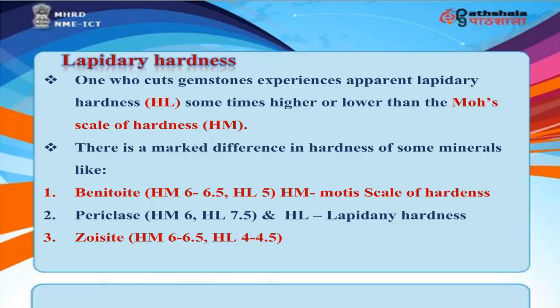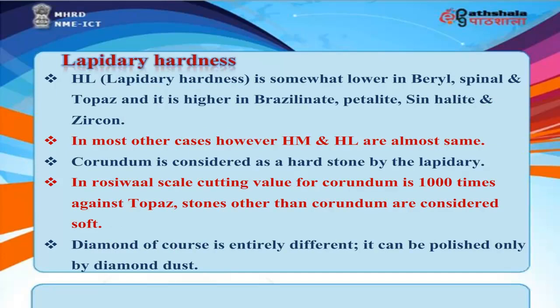Lapidary hardness. One who cuts gemstones experiences apparent lapidary hardness, HL, sometimes higher or lower than the Mohs scale of hardness, HM. There is a marked difference in hardness of some minerals like benitoite, HM 6 to 6.5, HL 5. HM is Mohs scale of hardness, HL is lapidary hardness. Periclase, HM 6, HL 7.5, and zoisite, HM 6 to 6.5, HL 4 to 4.5. HL is somewhat lower in beryl, spinel and topaz, and it is higher in brazilianite, petalite, sinhalite and zircon. In most other cases, however, HM and HL are almost the same.